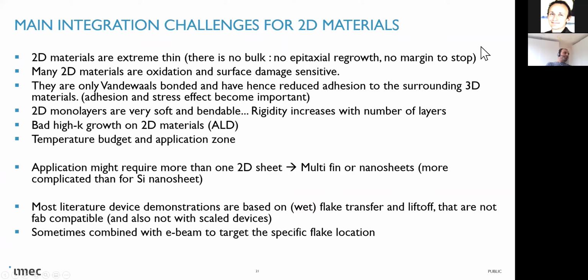And this is new, because in silicon we very often clean up the interface to prepare a better interface by a pre-sputter clean or whatever, but this is all impossible to achieve.